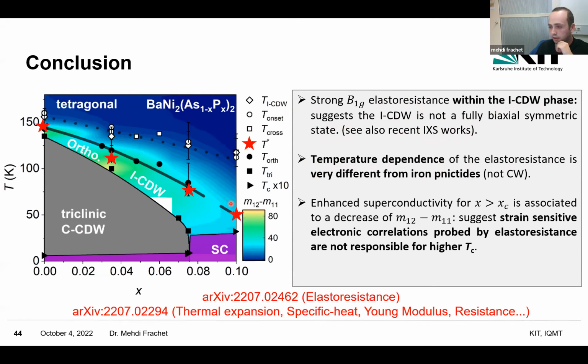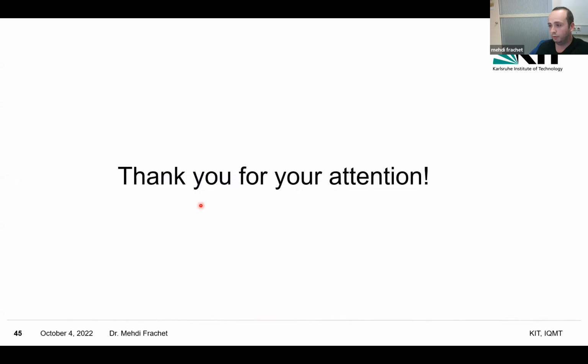And what you can see is that the strength of the B1G elastoresistance actually decreases with phosphorus substitution, which suggests that the strain sensitive electronic correlations that we probe are not responsible for the high Tc, or the 3 Kelvin Tc, on the high phosphorus side. And with that, I would like to thank you for your attention.